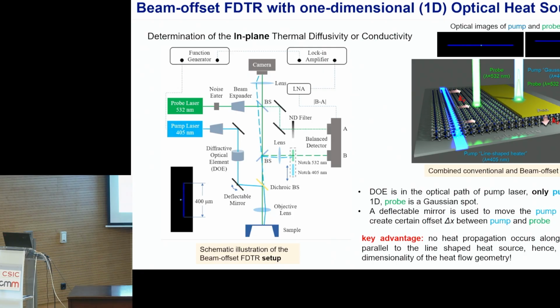So for this line-shaped heater, we modulate the pump laser. This is the pump laser that creates the heat flux in our 2D material. And with the green laser, we probe the temperature. So the left part of this image is how we measure the in-plane thermal conductivity in our material. And the key advantage here is that we don't have any heat that propagates along the direction parallel to the line-shaped heat source. This is very important because somehow we boost the heat flux to go in the in-plane direction. So we create a temperature gradient in the in-plane, and then we can go with the laser with a Gaussian beam and probe the temperature.